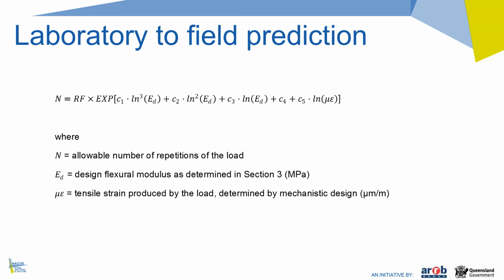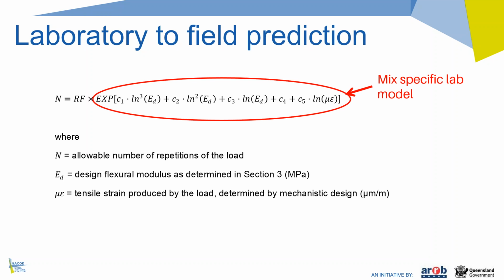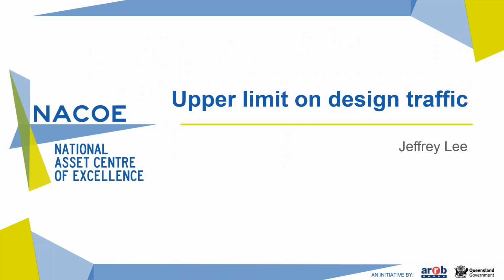So once we've got that laboratory model, we need to predict field performance from that, and we'll be doing that using the same reliability factor. So all we're doing here is replacing the Shell general laboratory model for mean performance of 12 mixes with a mix-specific laboratory model, and we're using the same laboratory to field shift factor to predict from that laboratory performance to field performance. Thank you.